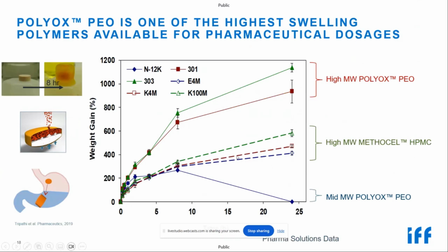In comparison, we have high molecular weight Methocel HPMC shown in the dashed lines. These show about half as much weight gain as we get with the high molecular weight POLYOX PEO. The green dash is Methocel K100M, and this is one of the highest molecular weight HPMC polymers we offer.